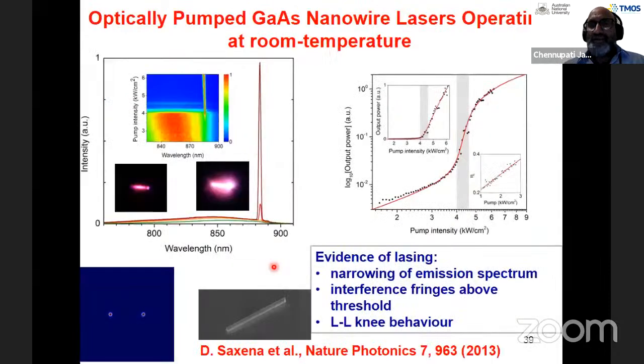So based on Drew Saxena's calculations, Dr. Jenny Jiang, who is at Cambridge University now, has grown these gallium arsenide, aluminum gallium arsenide core-shell nanowires of about 6 microns long and transferred them onto a glass slide here. And Drew Saxena did these measurements, and he excited the laser with a pulse and looked at the light coming out of these ones. You can see a very broad light emission below threshold, and above threshold, you see a very sharp light emission. That's what you would expect from a laser.